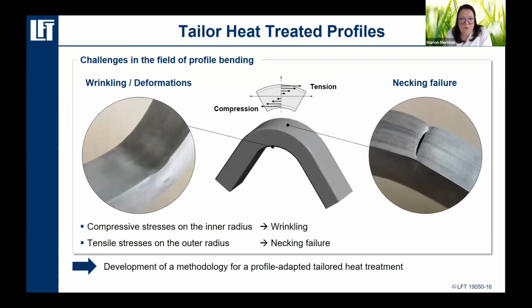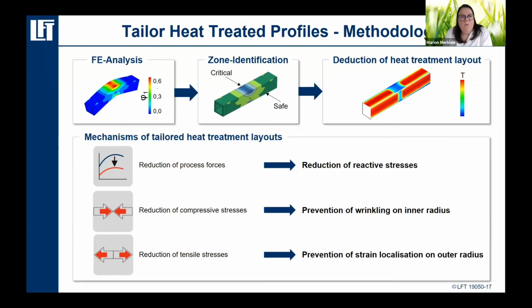But the problem with the profiles is that, again, wrinkling and deformation and necking may occur. And this can be seen as a result of the compressive stresses and the tensile stresses that occur. And of course, if we have such a wonderful method for the deep drawing operations, then we are sure that we can apply it also on such profiles. And what you can see here is, yes, it works. The most important aspect is that you have to take into account the different stresses that are applied in different